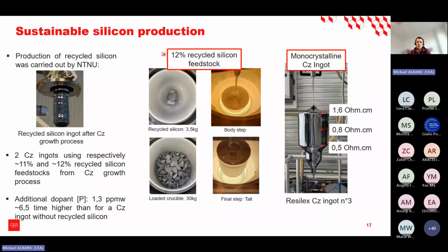So you can see the picture of the experiment. You can see here at the bottom of the crucible, the recycled silicon coming from here, and then the crucible loaded with 30 kilograms of silicon. And here I chose a picture of the body step. So during the pulling step, you can see the seed used, the neck, the top part of the ingot, and here this is the interface between the ingot and the silicon melt, and all these parts are in the heat shield.